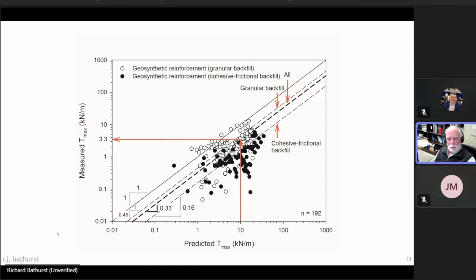So here on the horizontal axis is predicted load, and on the vertical axis, the measured load. And if you had a perfect model, these data points would all fall on or close to the one-to-one correspondence line. But this is clearly, at least visually, not the case. And in fact, what we found was that on average, the measured tensile loads were about a third of those predicted using the current ASCE simplified method. In addition to that, not only were the mean predictions of load hugely conservative, but the distribution of loads, as I will show later, was also poorly predicted by this simplified method.